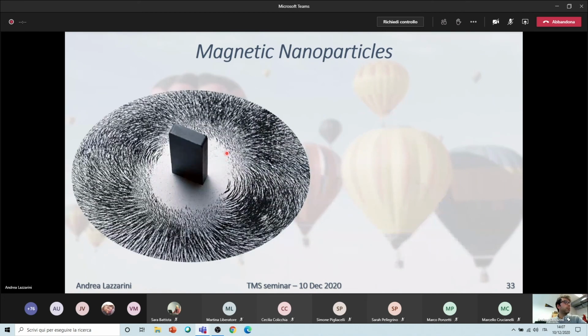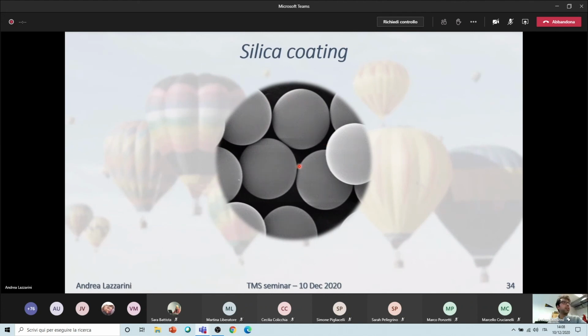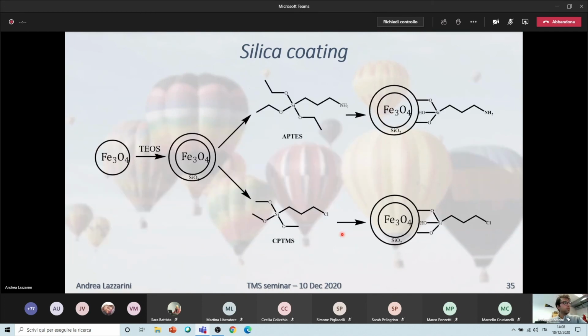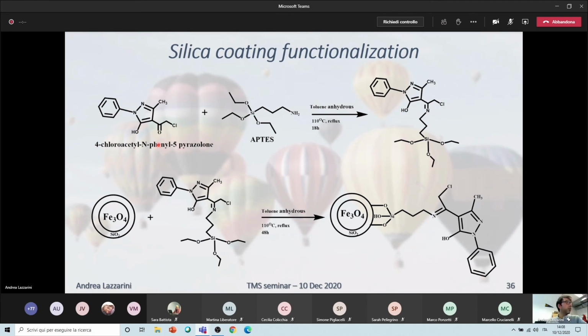But the magnetic nanoparticles and the magnetic fields in themselves are very fun. You can do a lot of things with them, but if you don't cover them with something, they might interfere with the catalysis that is your final goal. For these reasons, we were covering our particles with silica, which, as I told you before, provides a very nice shielding, and it's inert to almost all reaction environments. It's also easy for it to provide an anchoring point for further functionalization of the active phase. So basically we were producing magnetic nanoparticles covered with silica, and then functionalizing with organosilanes that are able to undergo further functionalization with any kind of anchoring molecule.